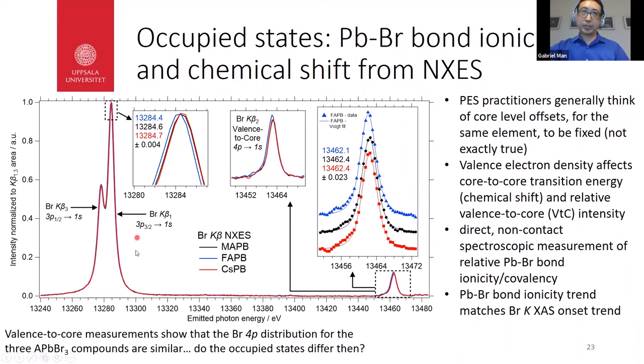So to check this deduction, we can look at the relative intensities of the valence to core feature with the K beta 1 features, with the core to core lines all normalized. Here we see that the blue trace shows a little bit more intensity. So that seems to be consistent with this deduction that there's a more ionic lead bromine bond for formamidinium lead bromide. This core to core transition energy trend seems to hold for the valence to core as well.